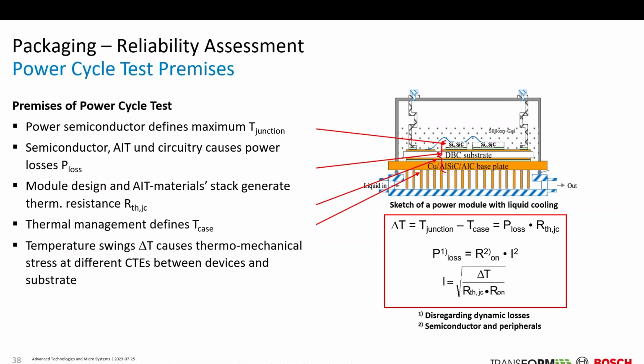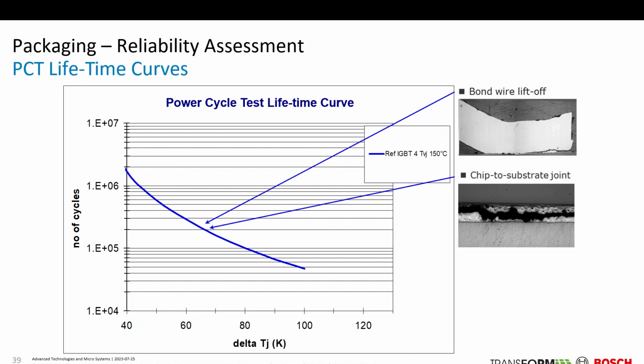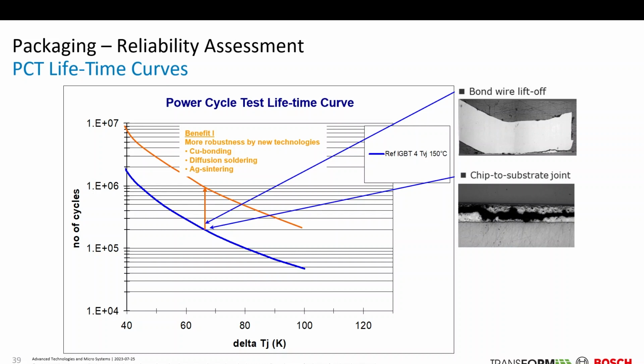So you see these influencing factors, you need information about all of them to derive a proper situation for the power cycling test again. This is a typical lifetime curve, the blue one. You see maybe for a certain lifetime data point, you see then degradation as a bond wire lift-off, for example, or degradation in your die attach here. And then you can change this technology, the base technology, as shown by the slides, for the sintering or something like that, or the change from aluminum bonding to copper bonding. Then you will shift your lifetime curve to higher values here, but it has twofold benefits.